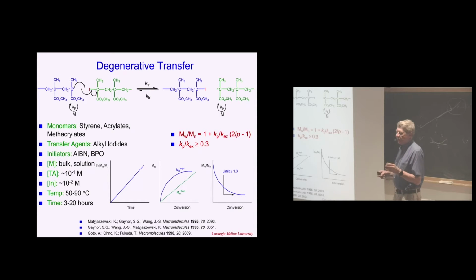So the problem with this alkyl iodide is a very simple system because it would be degenerate transfer. Whatever you have on the left side is the same as on the right side. The problem is that it is not fast enough, which means that the ratio of propagation to exchange reaction is very comparable to unity. Because this exchange reaction will be bimolecular with another alkyl iodide, and alkyl iodide will be at a concentration 100 times lower than monomer. It means that you would add 100 monomer units before you exchange. So you don't go 1, 2, 3, 4, 5, you go 100, 200, 300, so the molecular weight distribution will be much, much broader.